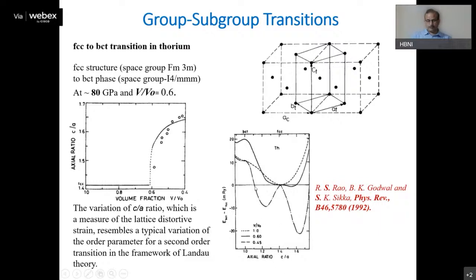If you plot this free energy as a function of the c/a ratio, actually you can make it c/a minus square root 2, so this will become 0. So this dotted line corresponds to the initial phase, where the minimum is at the c/a ratio of 1.414. But as you increase pressure, this energy well modifies, and you get these two minima. So this clearly shows this is a phase transition, a kind of continuous phase transition, because this c/a ratio continuously evolves from this value.